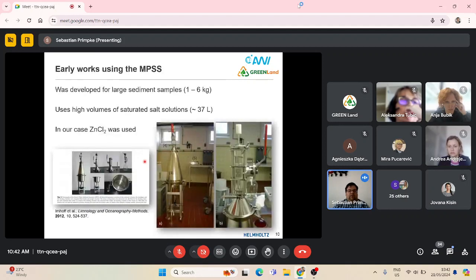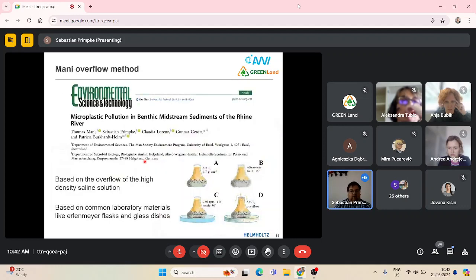And when we started, we were aiming for large samples. So we used this microplastics sediment separator, commercially available. We need 37 liters of a saturated salt solution. We started using zinc chloride and aimed to have at least 1 kilogram of sediments. That worked quite well, but then we had the issue that we have only 20 grams of sediment to analyze. It doesn't work in the MPSS.